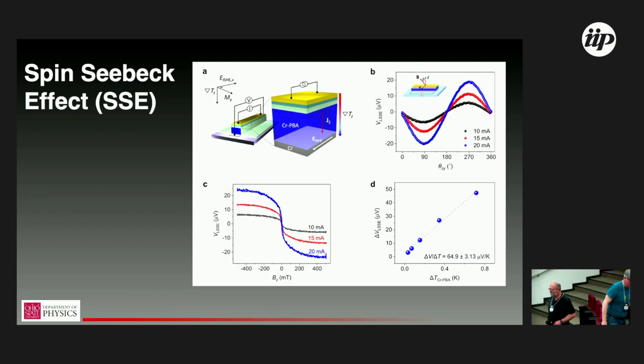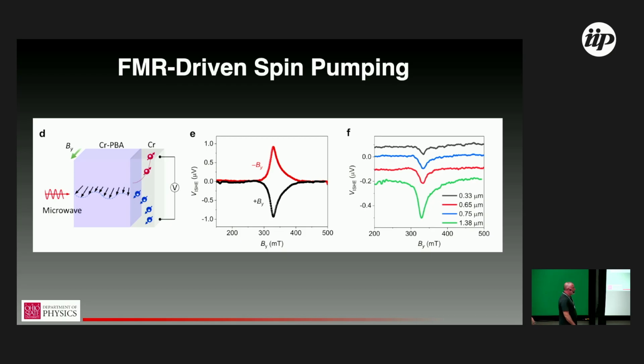The magnetic material here is generally not a good conductor. So for the transfer across the interface, and maybe this diagram is a little easier to see, the interaction at this interface is a pure spin-spin interaction. It's an exchange coupling between the magnons on the one side and the conduction electrons in the conductor on the other side.